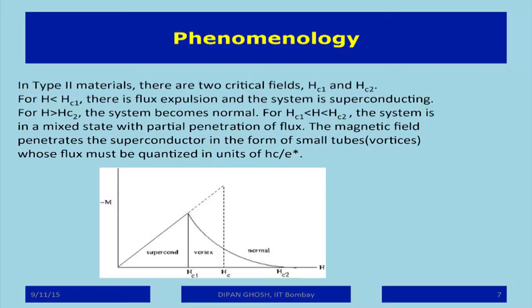But if it is not large enough, yet greater than some value Hc1 but less than Hc2, then one finds a partial expulsion of flux. This can be called a mixed state. The reason I cannot go into is that certain tubes of flux can actually enter the specimen. These are also known as the vortex state. What happens between Hc1 and Hc2? That's a mixed state, so it remains partly superconducting.